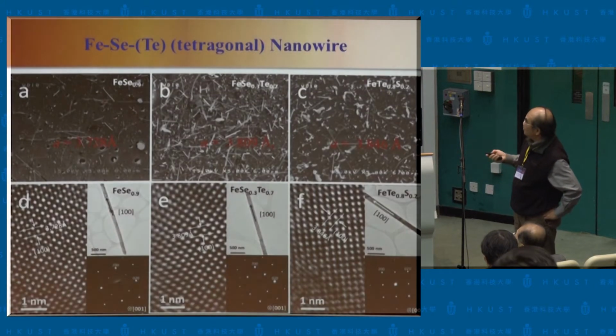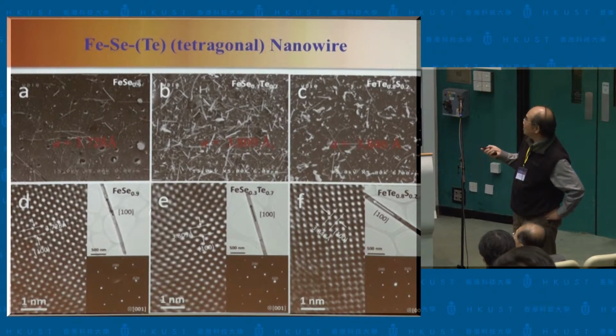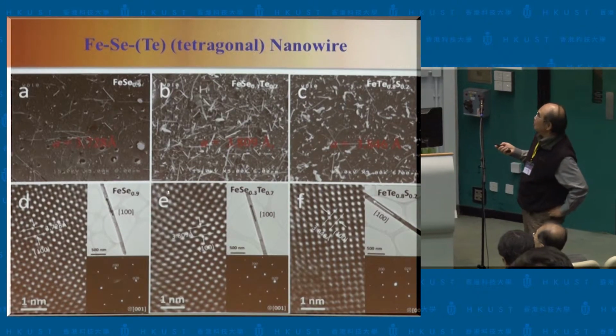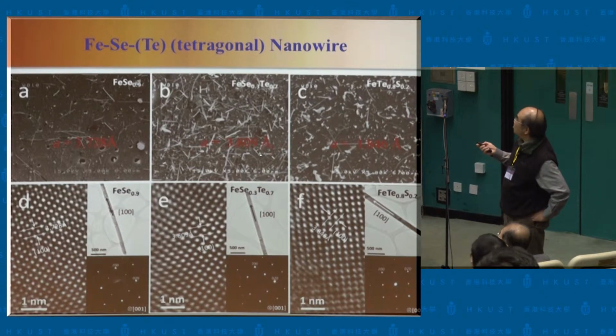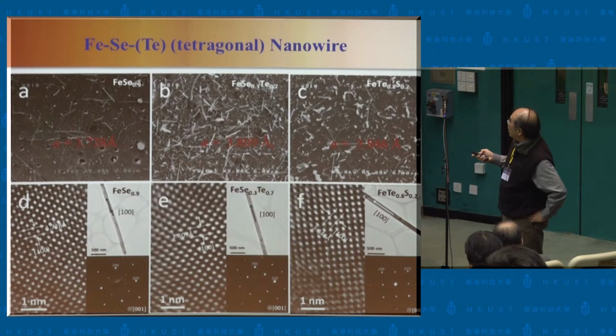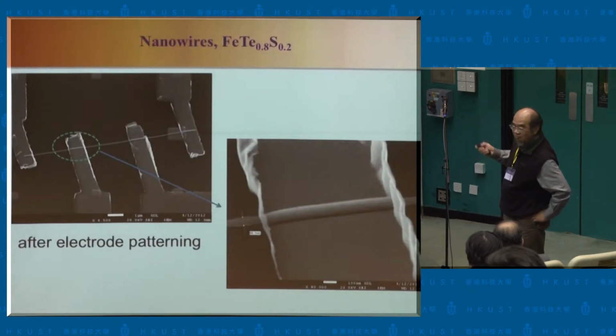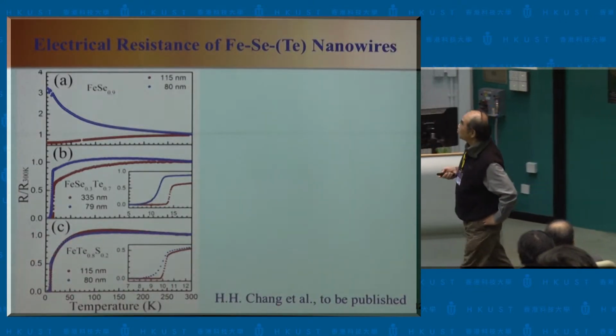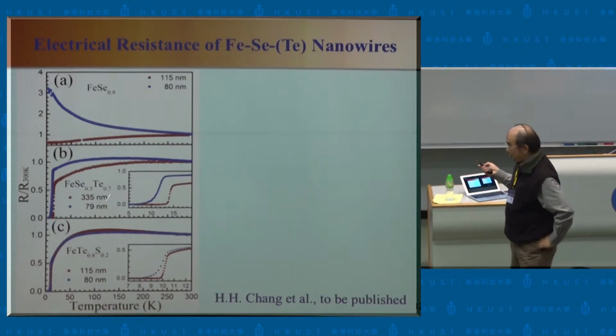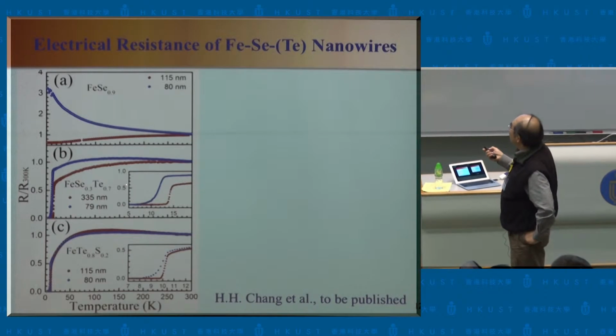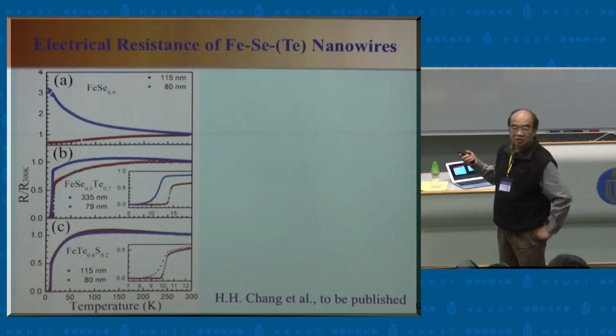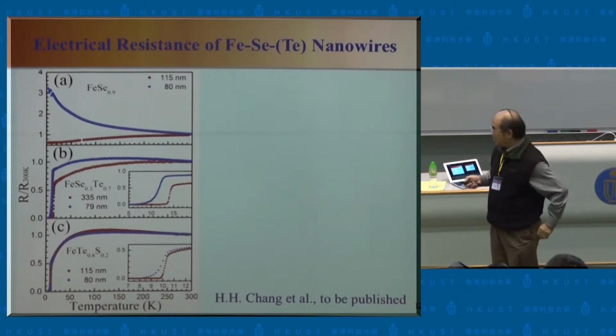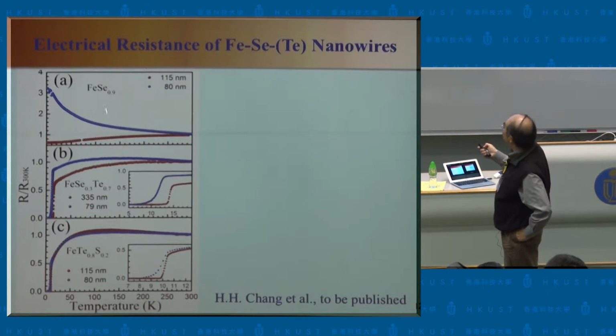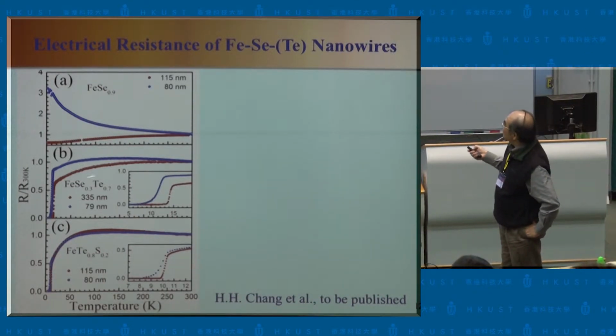Okay. So we developed another technique to grow very high quality nanowires in the dimension of 100 or tens of nanometers. And the lattice parameter is always found to be a little bit smaller than the bulk. Okay. And then we were able to make the contacts and do the measurements. And that's what we saw in several of these iron selenide nanowires. Okay, here, this is the iron selenide. Unfortunately, so far, we have not been able to really see the resistive transition in this iron selenide nanowire, which is actually probably important for us to understand what's going on here. But for the selenide with the tellurium doping or this tellurium sulfide, here there's an interesting feature I want to mention.